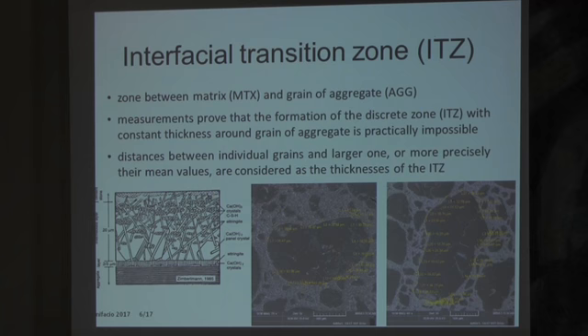The other advantage of the microstructure measurement is that we can measure the distances, also in 2D, but we can use it. You can see on this picture, I hope, this is the grain of aggregate. It's a larger grain of aggregate, and it's not so easy to define a constant thickness of the ITZ, because as you can see in the micrographs, there are different structures around the grain, and it's not so ideal as in this picture, where there is a constant thickness of ITZ.